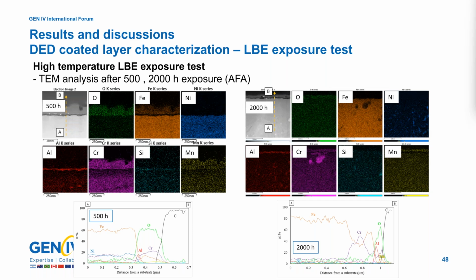The AFA coated layer forms an oxide layer with an outer composition of iron oxide and iron chrome oxide, and an inner layer of thin and dense aluminum oxide, which leads to higher corrosion resistance by preventing oxygen penetration and metal dissolution.